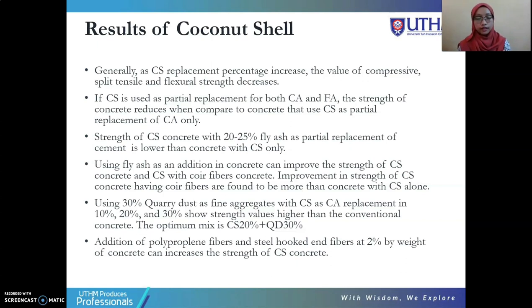Using 30% quarry dust as fine aggregate with coconut shell as coarse aggregate replacement at 10%, 20% and 30% shows strength values higher than the conventional concrete. The optimum mix with the highest compressive strength is 20% coconut shell and 30% quarry dust. Lastly, the addition of polypropylene fibers and steel hook end fibers at 2% by weight of concrete can increase the strength of coconut shell concrete.